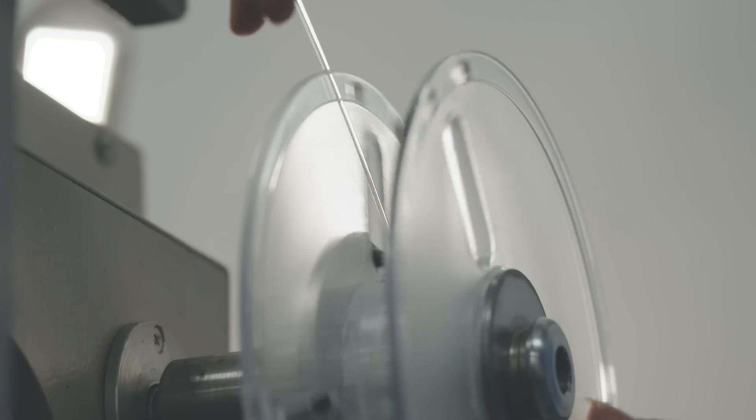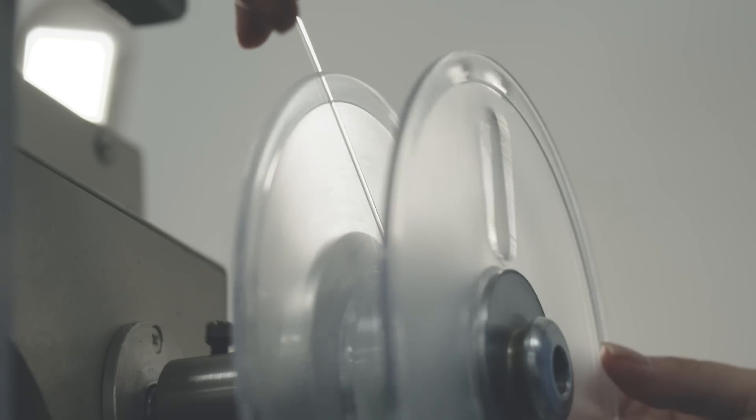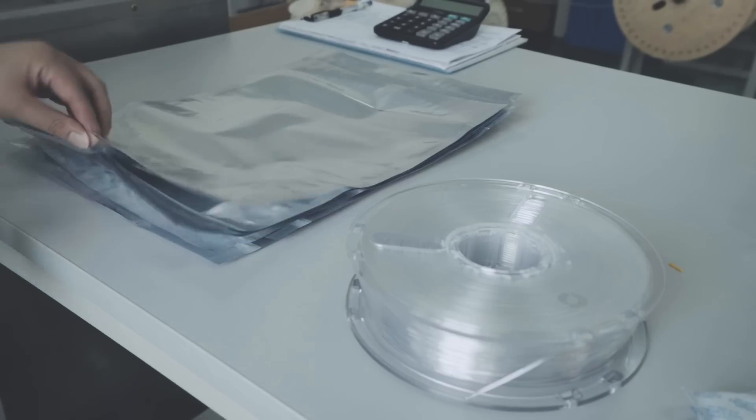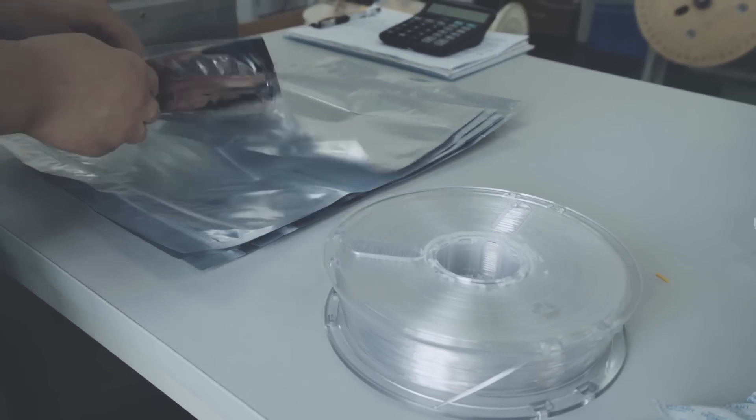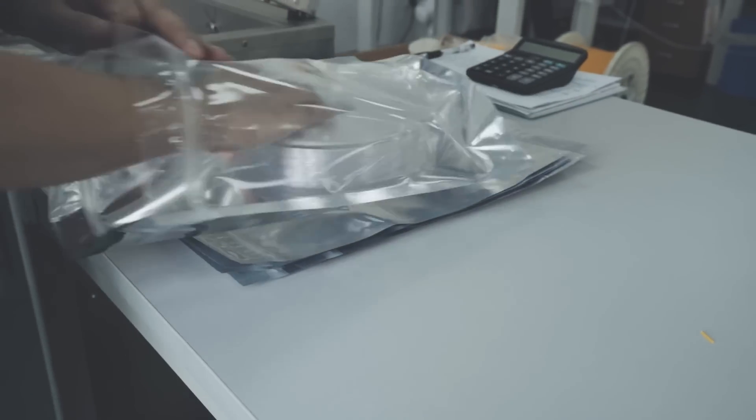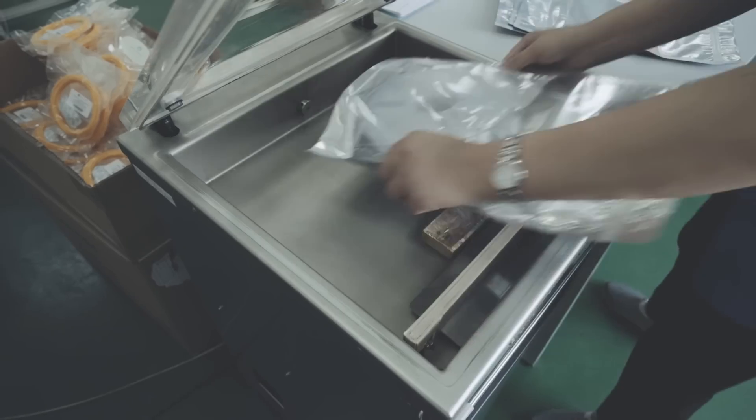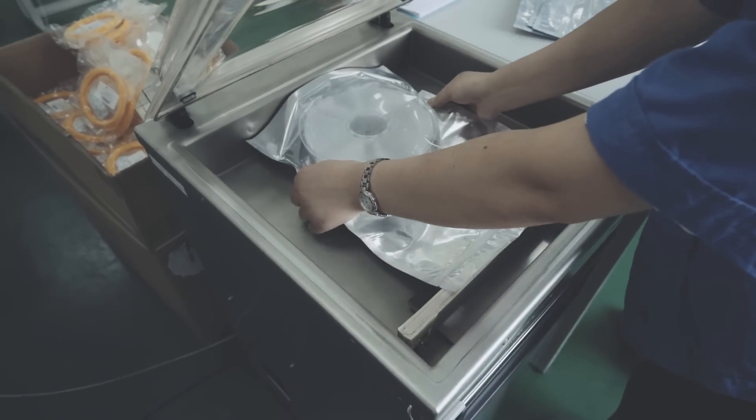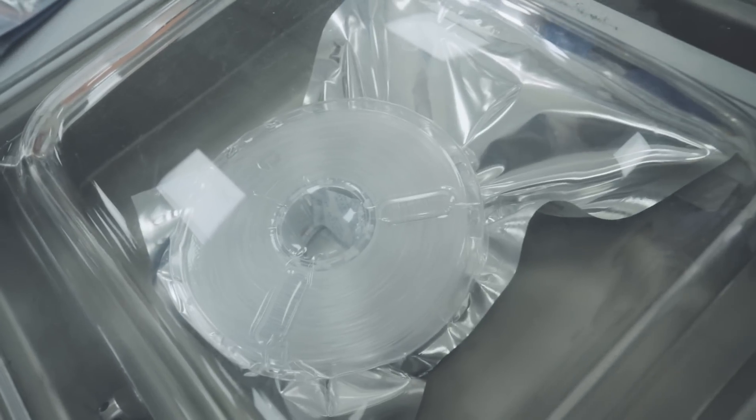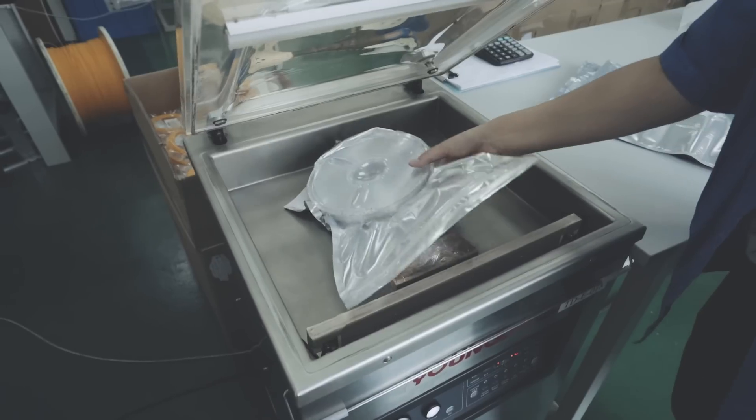Sent off to the spoolers, carefully and perfectly aligned. I'm spooled in flawless formation, dried in an oven for 24 hours, then suffocated of air and moisture as I'm individually vacuum packed into a resealable bag.